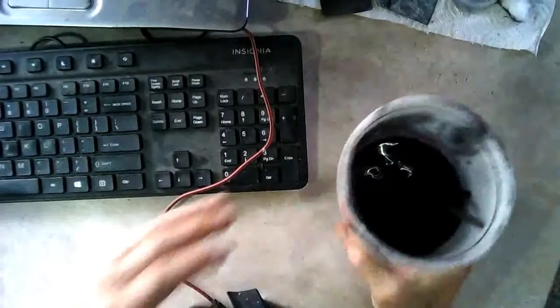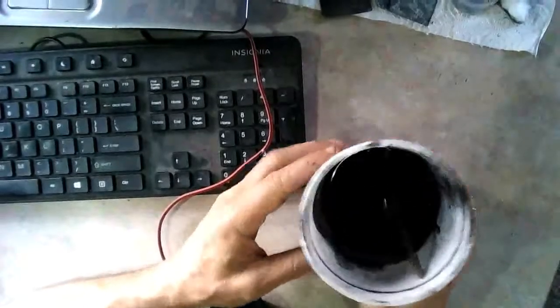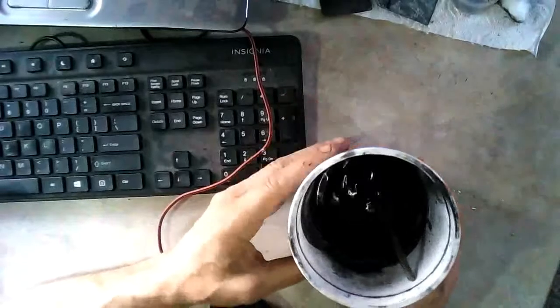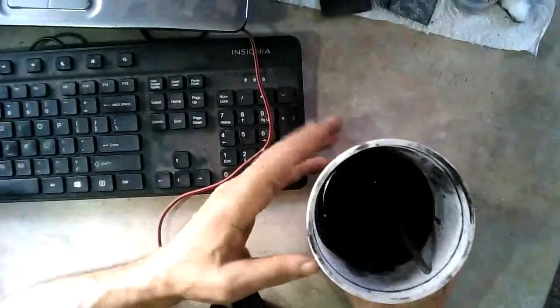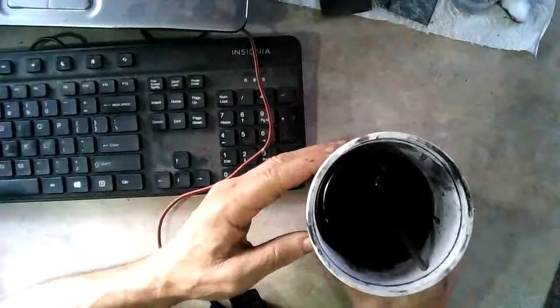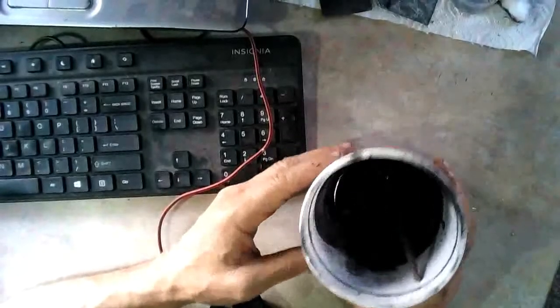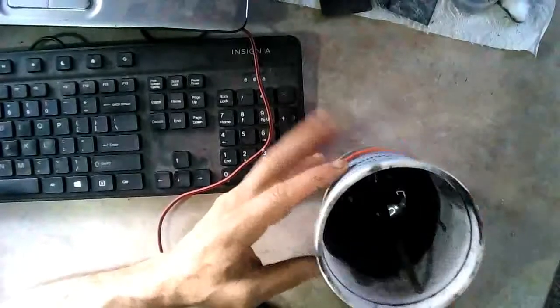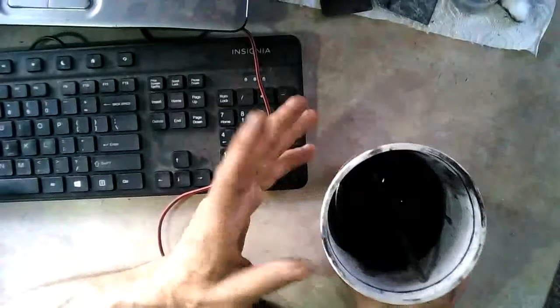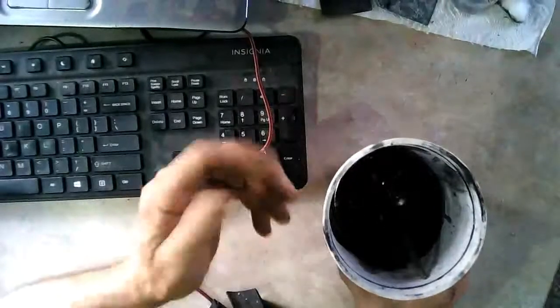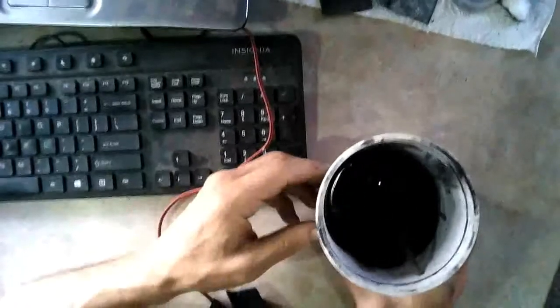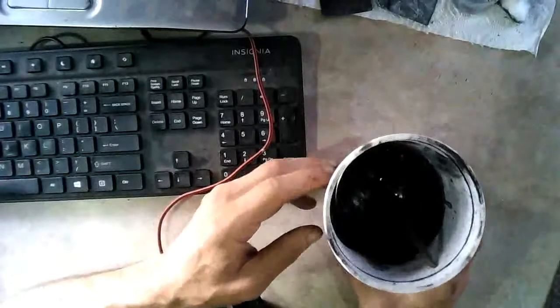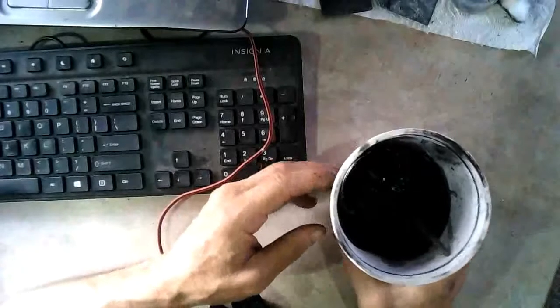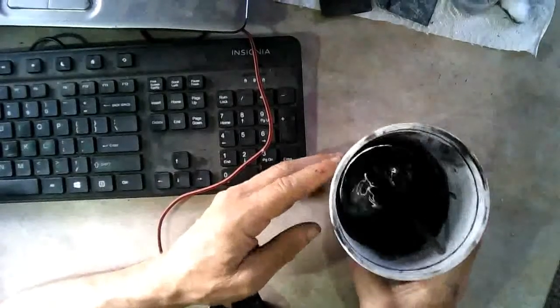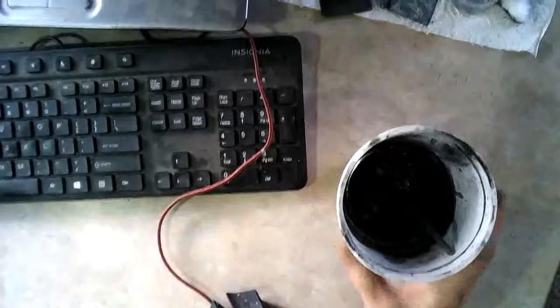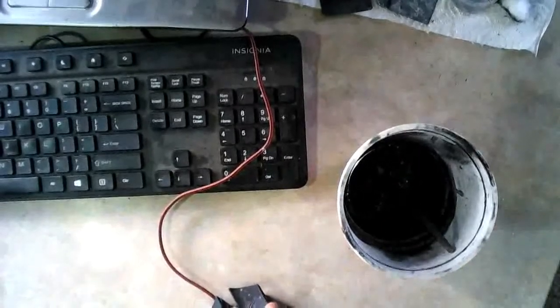Alright, this is the first batch of intercalated graphite that I made. What I did with this was I poured off the excess graphite liquid that was in there, so it just left the solidified stuff in the bottom of it, and then I put some distilled water in there and rehydrated all that, and now I'm sonicating it. It's had about a half hour of sonication, and I'm going to sonicate it some more, and then we'll see how that turns out.